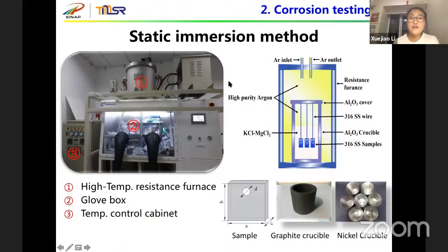The static immersion method is the most common method. The left picture shows our experimental equipment, including the high temperature resistance furnace, the glove box, and the temperature control cabinet. Here is the core component. Several perforated samples are suspended in the molten salt, which is put into a crucible, where the choice of crucible depends on the species of molten salt. All the corrosion tests are carried out under argon atmosphere.